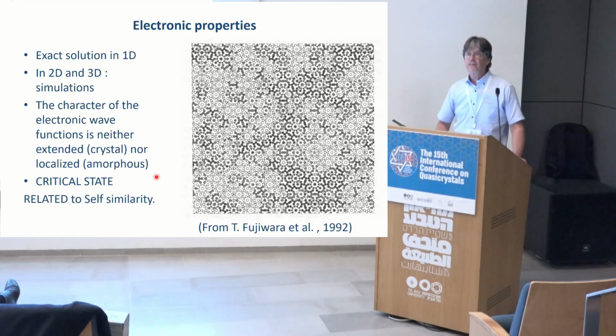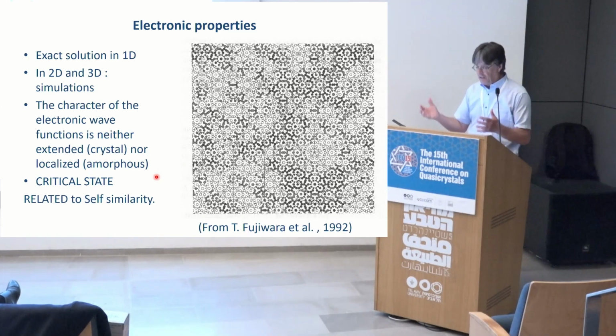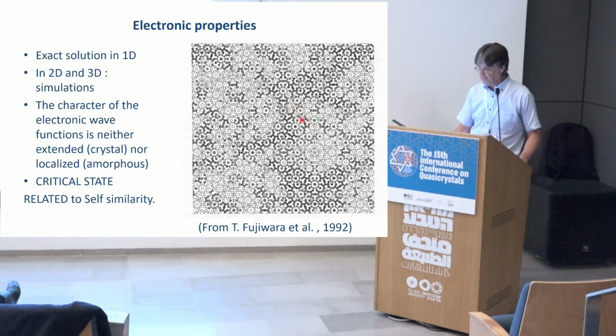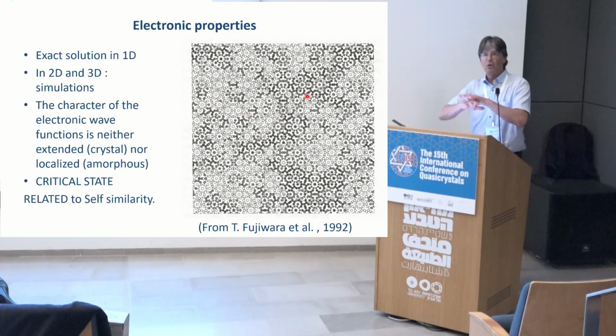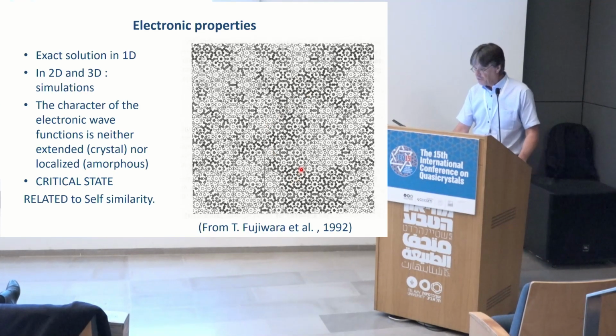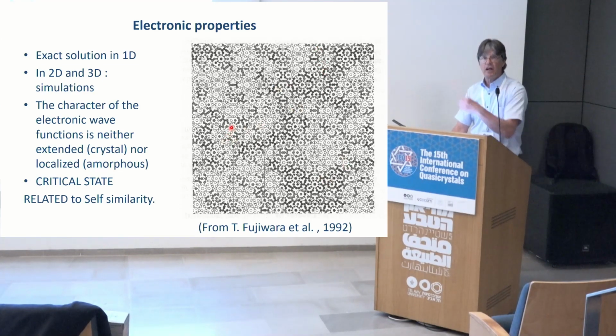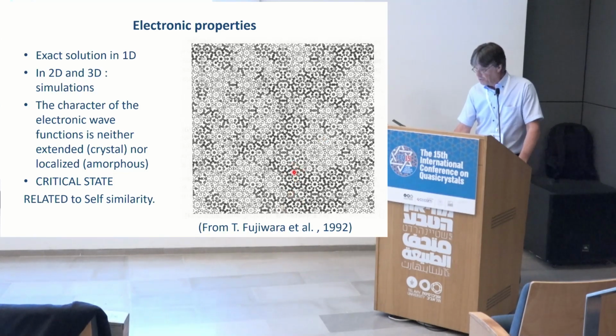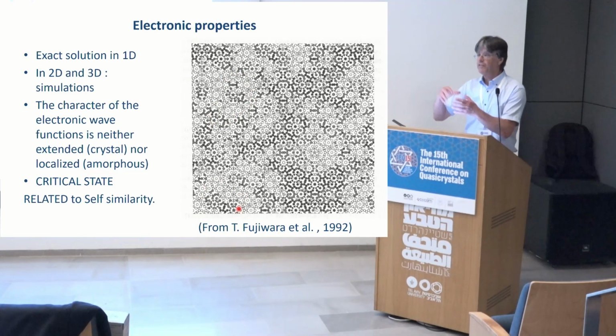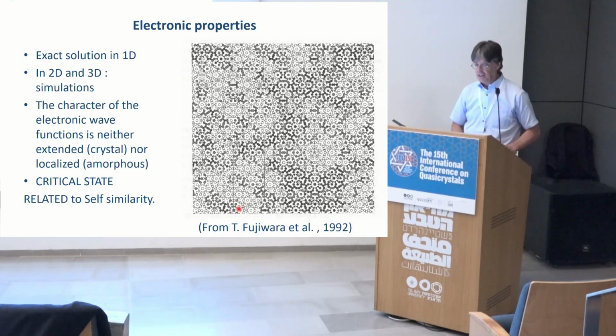Electronic properties, I think electronics or phonons, these are quite similar. One very peculiar prediction made by theory is that the electron wave function should be what they call critical. It's neither extended all over the crystal as in a simple crystal, nor localized as it is in a simple disordered system. It's rather displaying the underlying self-similarity of the structure. And you see here an example taken from Fujiwara, where the electronic wave function is strong when it's dark, and it's dark where the local environment is the same. It's weak here. If you take this weak part, it's the same as this weak part here, or the same as this weak part. So the fact that you have this underlying self-similarity is playing a specific role and should give rise to very specific electronic properties.